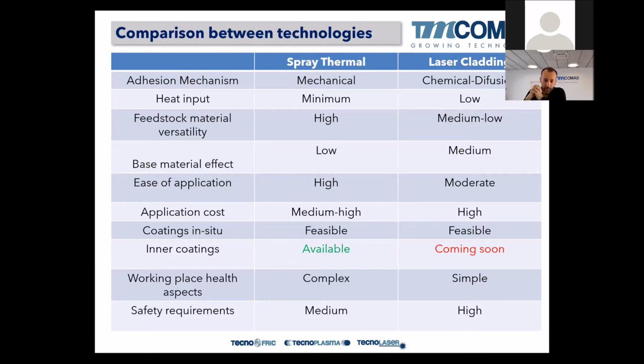The possibility to apply coatings in situ in thermal spray is possible. We can spray a lot of boiler tubes, for example. Not with all techniques, but with some techniques that are more portable, so it's possible. While in laser, it's possible also, but it takes more. It's more complicated. You have to take a laser, a robot for the movement. The fiber cannot be very long, so you have a restriction from the laser source to the cladding head. So it's more complex to work in situ with the laser, okay?